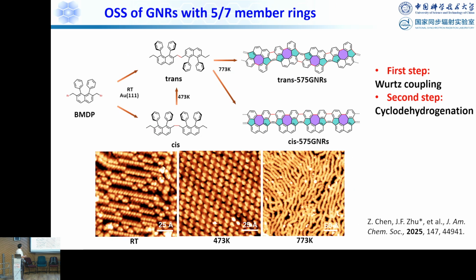Okay, so the next example that we want to show is that we have observed 575-membered-ring graphene nanoribbons on the surfaces. With this precursor, first the Wurtz coupling happens, and then second, if you heat up the sample, you get the cyclodehydrogenation reaction. At the end, you will form this trans and cis. At low temperature, room temperature, it mainly forms the cis structure, and with further heating, the cis structure can convert to the trans structure. And then if you go further, heating up to 773 Kelvin, then you can form these two